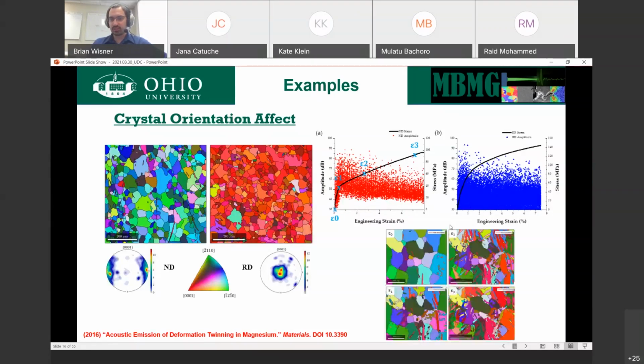The reason is that the microstructure is evolving differently. The case here where we have the predominantly red orientation, which corresponds to the situation, we have predominantly dislocation type motions leading to failure. In the case on the left, the ND samples, we actually induce a mechanism called twinning. So we're causing a specific damage mechanism to happen to change the behavior. Usually we like to avoid these twins in order to ensure we don't nucleate cracks and fatigue. So knowing this, we can actually choose material orientations and subsequently choose material manufacturing processes that can give us that preferential direction.